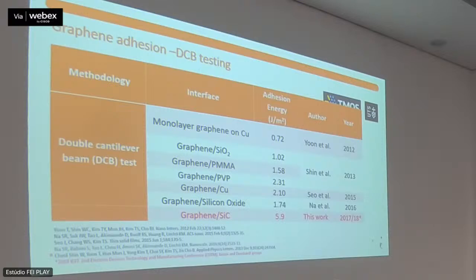Now, this might not say much to most of you, but when I was working with integration, this would be the low end of the application of, for example, low-k dielectrics, where no CMP would ever work, because everything would break down and collapse and be very ugly and destroy the yield of the system. So basically, no one really wants to work with that side of adhesion energy integration. Now, it turns out that we measured the adhesion energy of our system, and the number we obtained is about 3 times higher, so 6 joules per meter squared.